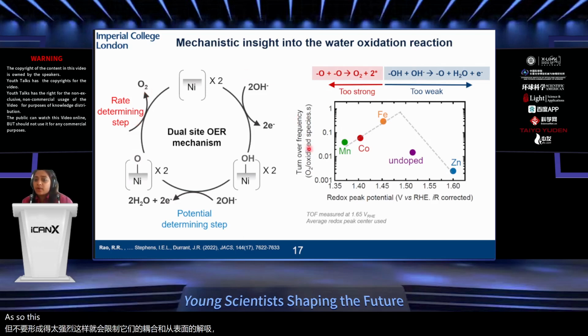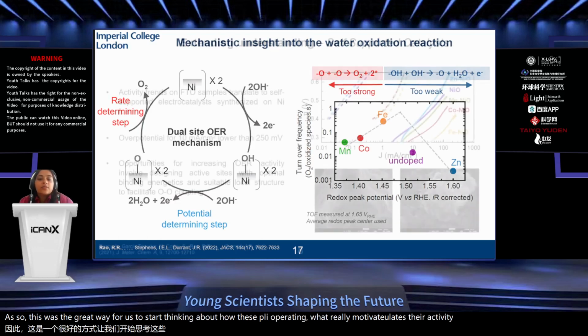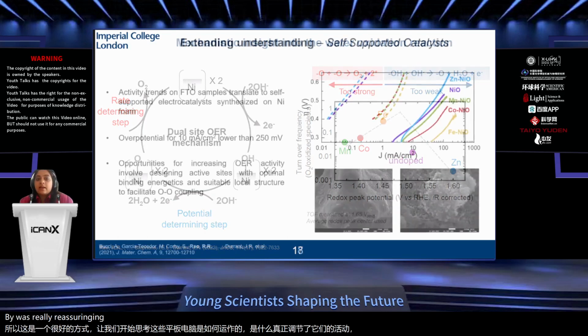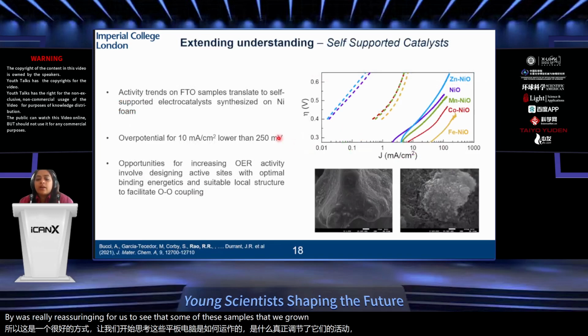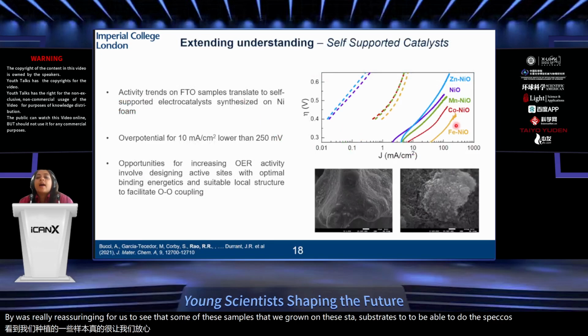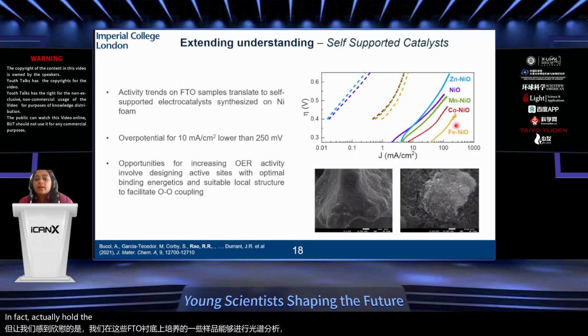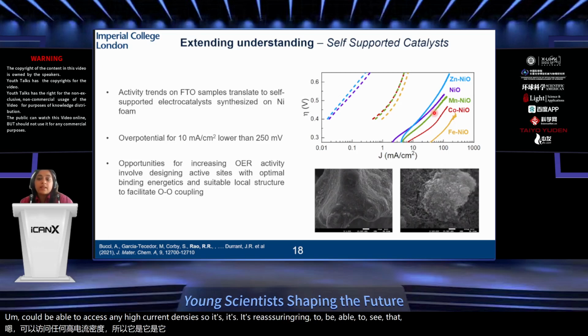So this was a great way for us to start thinking about how these catalysts operate and what really modulates their activity. It was also really reassuring to see that some of these samples that we'd grown on FTO substrates to do the operando spectroscopy hold the same trend when you deposit them on three-dimensional metal supports to access really high current densities. So it's reassuring to see that a lab scale trend also holds under more industrial settings.